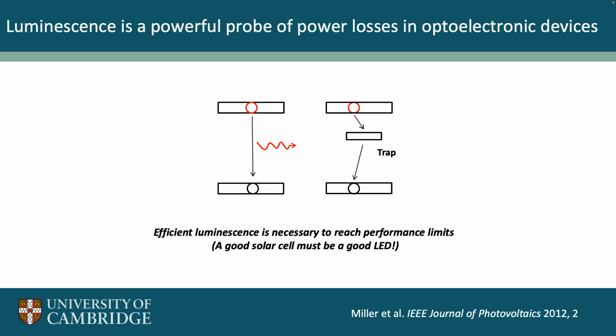But if there are traps or defect states, then these electrons will instead hit one of these defects. They essentially get physically trapped in one of these states, and then they lose their energy to heat, and therefore we don't get a photon out. So we can use this to assess which samples have traps, because we want to maximize the light coming out from these solar cells. It's counterintuitive, but a good solar cell should also be a good LED. We should be able to put electricity in and get light out, and we use this reciprocity very frequently in our labs.